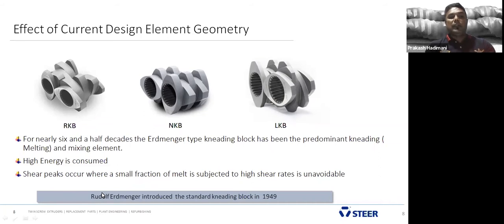And also it liberates peak shear. The peak shear is not acceptable for low bulk density, or you can say natural fibers, because the peak shear degrades fibers and liberates black specks. And some of them, say a flame retardant application, and very sensitive materials, okay, it is not acceptable for a peak shear.